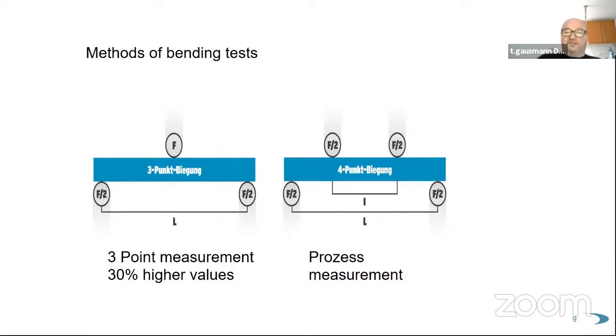We polish our specimens and either put them into a 4-point bending test, making the area of measurement much larger, or we put them into a biaxial test. Then you've got 3 small spheres underneath and a central sphere pressing from above. Having a much bigger area to measure gives you a process measurement. So what you measure here is, it can break here, here, here. You've got possibilities all over between these 2 points that you get a crack and that it will break.